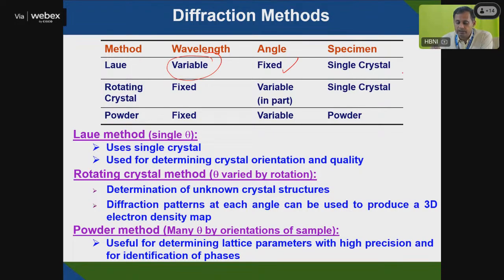So you can do single crystal analysis by using different wavelengths. In a rotating crystal, you have a fixed wavelength and a variable angle. So your wavelength will be fixed, and you can vary the angle. Similarly, in powder diffraction, you have a fixed wavelength and vary the angle. Like in the case of copper, you take copper K alpha, and the angle is variable, and you will get the pattern in the powder diffraction method.